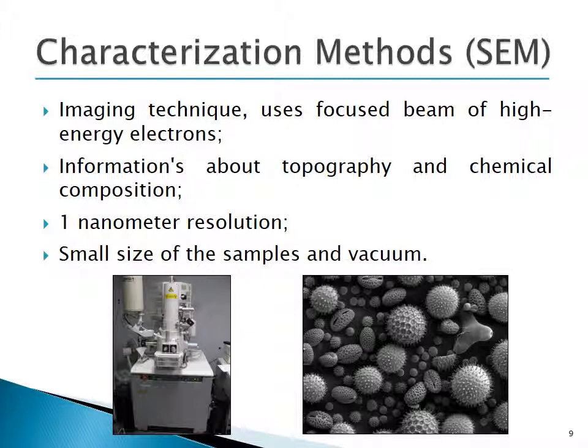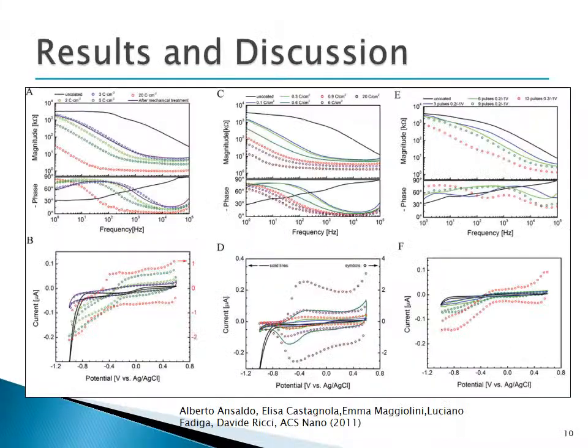Scanning electron microscopy is an imaging technique, and it uses a focused beam of high-energy electrons to study the sample. We can obtain topographic information or chemical characterization. A small area is chosen, and a raster scan of electrons is made, allowing resolutions of 1 nanometer. The interaction between the incoming electrons and the sample produces several particles, but only secondary electrons are analyzed by SEM, using a detector. It's an easy-to-use technique, however, it requires the use of vacuum and very small samples.